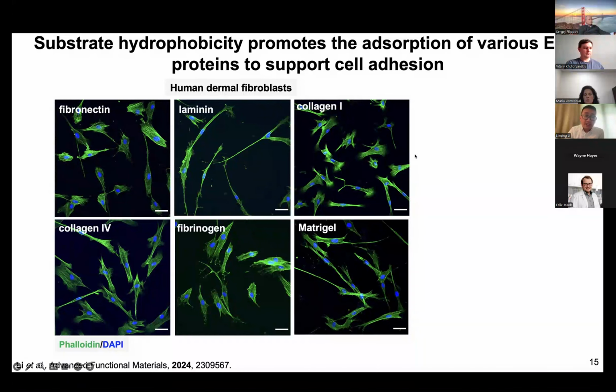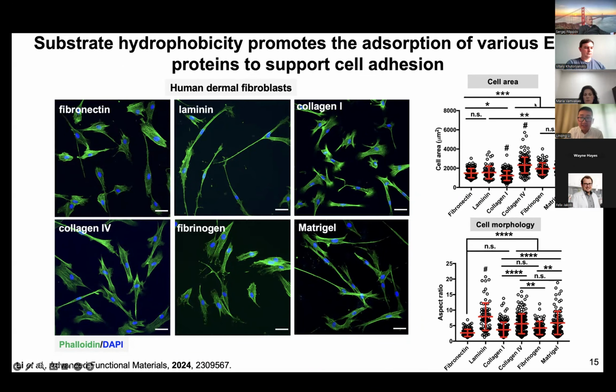And then collagen 1 is not, because the triple helical structure does not give a well-defined cell morphology in these cases. And then we quantify again the cell area. You can see the laminin and the collagen 4 have a larger cell area, as well as aspect ratio. The laminin and the matrigel had the highest aspect ratios compared to the other ECM-coated surfaces. So this again shows that we're able to develop this hydrophobic hydrogel platform that can be applied for a variety of different ECM protein absorptions and show that we have achieved ECM-specific protein